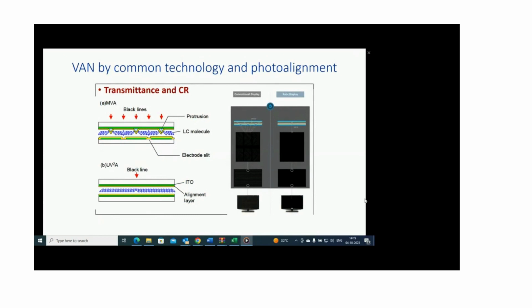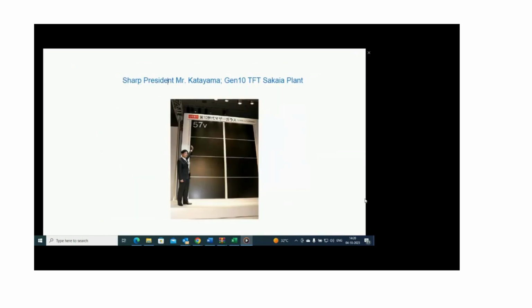You can look at this picture. Before, TVs used defects at the center of the pixel and patterned electrodes, but photoalignment can make angles very, very uniform, and you don't need to deal with defects and patterning electrodes. You can look at the picture here, and you can see that the bright state is extremely bright, and the dark state is much better. This technology is called UV2A technology, UV vertical alignment of liquid crystals made by photoalignment technology.